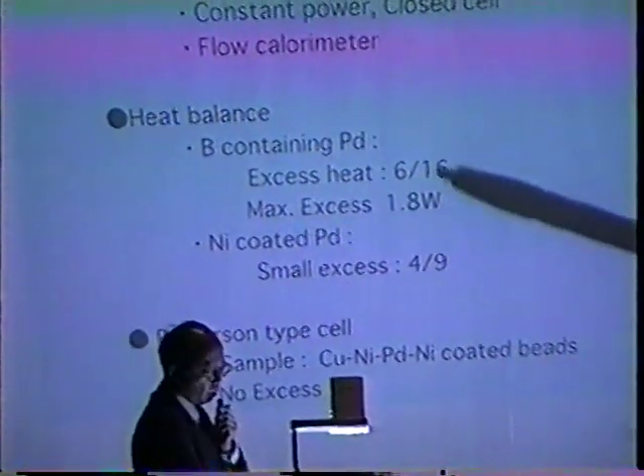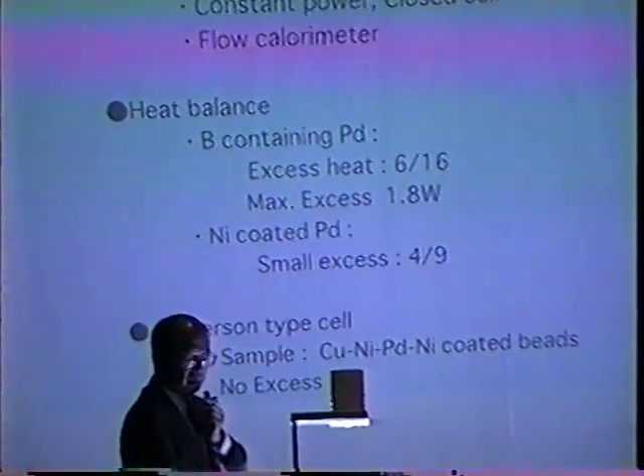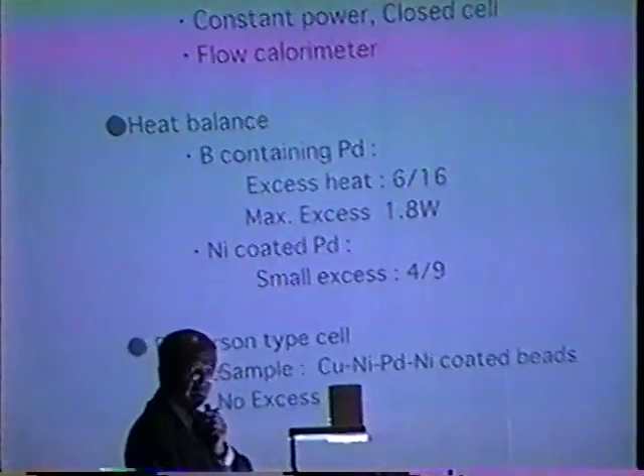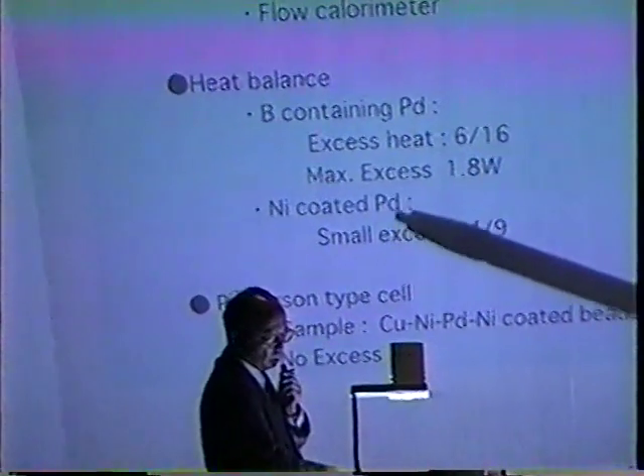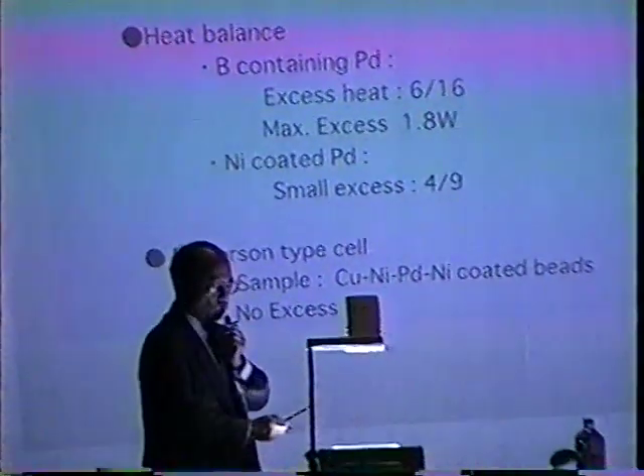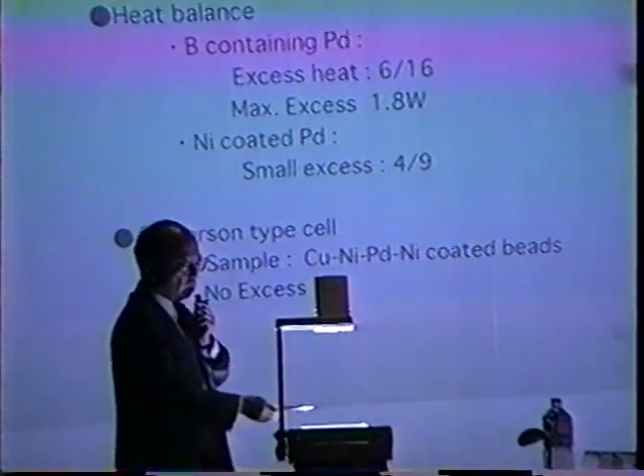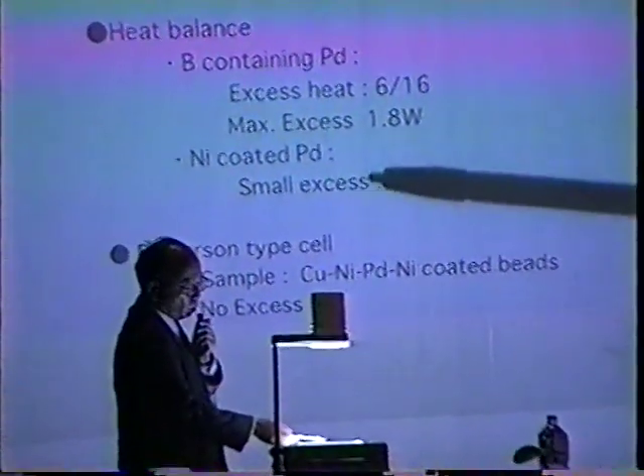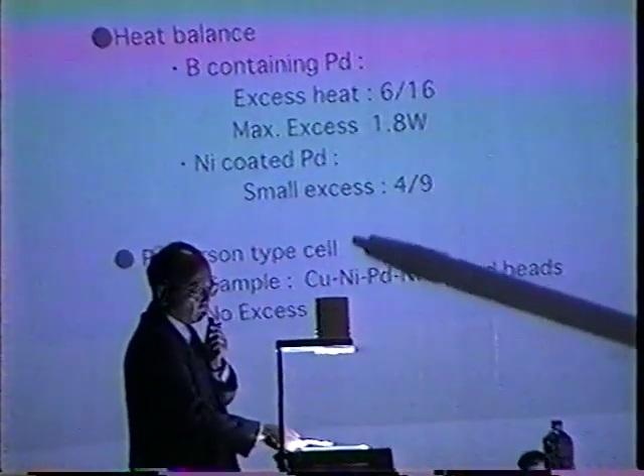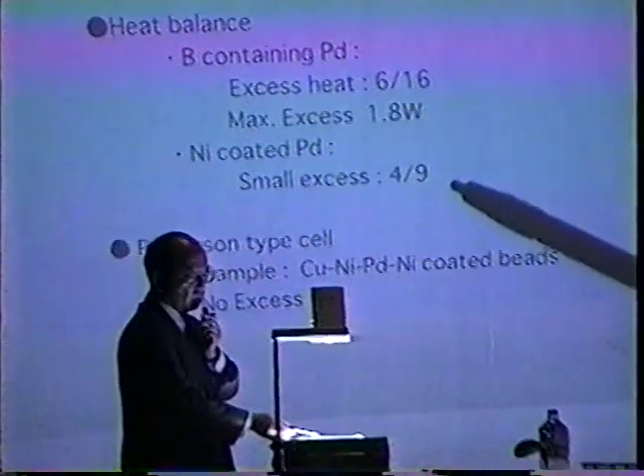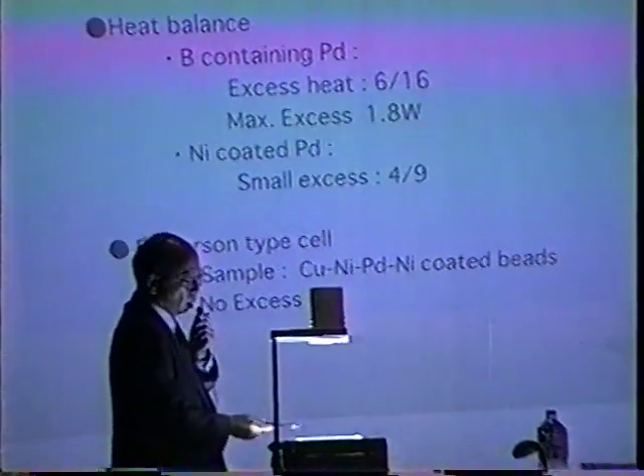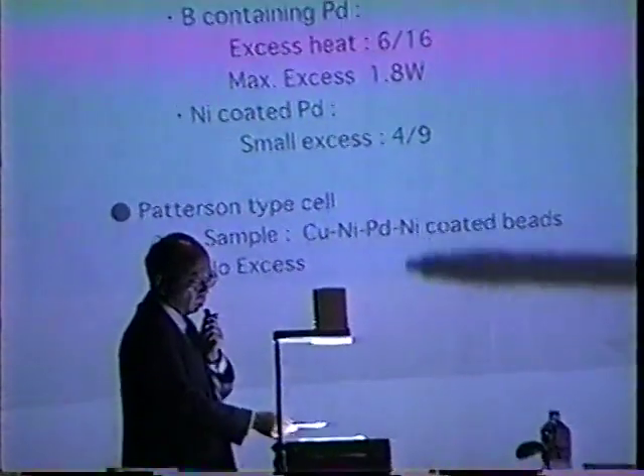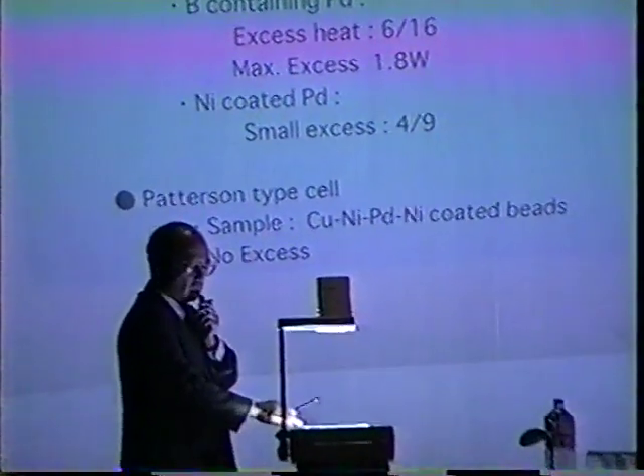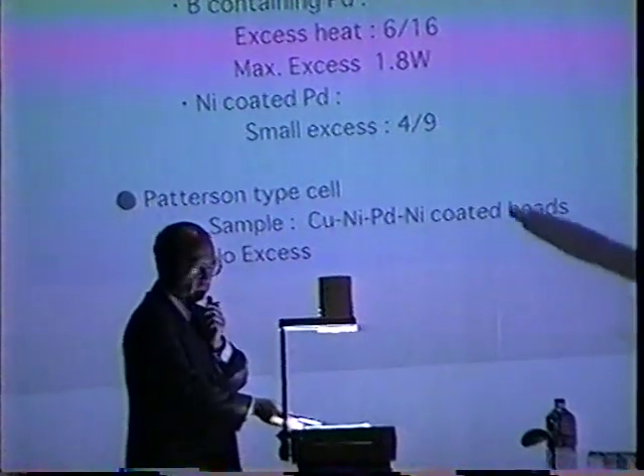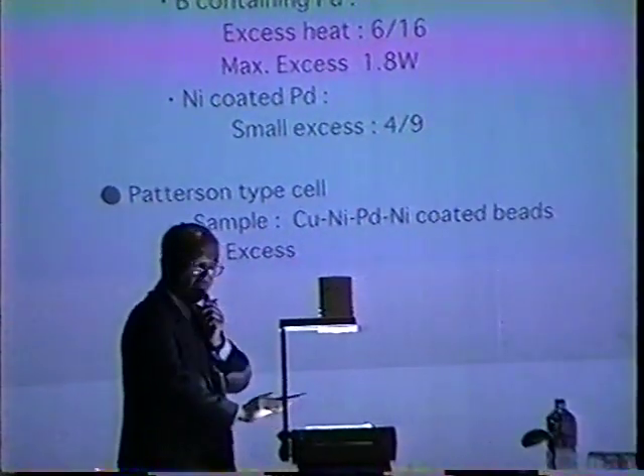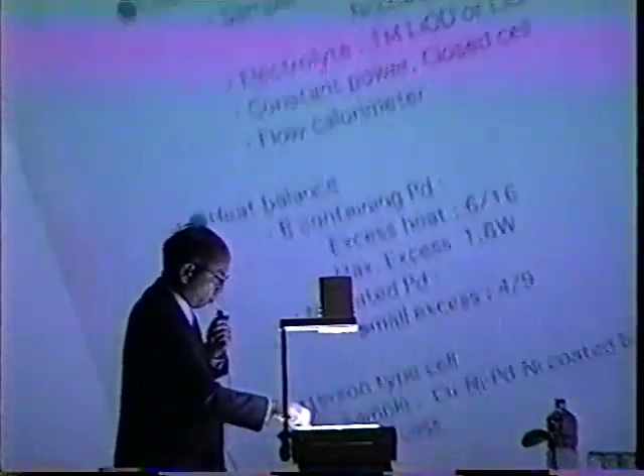For boron-containing palladium, we observed excess heat 6 times out of 16 experiments. Maximum excess heat we detected is 1.8 watt at an input power of 5 watt. For nickel-coated palladium, we observed very small excess 4 times out of 9 experiments. We also did some work on the so-called Patterson type cell using some special beads, but we didn't see any excess at that time.